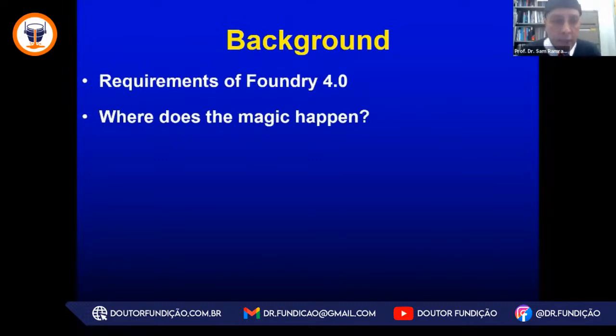In addition, an important consideration is some of the metallurgical concerns. Where does the magic happen? The magic happens where the molten alloy meets the sand, and in this case, a sand binder system. If we can imagine a recipe that has molten metal, it has ceramic media, and it has a polymeric binder or some other inorganic constituents. The point is, the chemical binder may give first. And if we don't have the stability needed there, it can be a concern for shaping the casting. But the point I ultimately want to make here is that the magic happens at the mold metal interface, and at the mold metal interface, there are thermomechanical, thermochemical, physiochemical, and thermophysical changes all happening at the same time